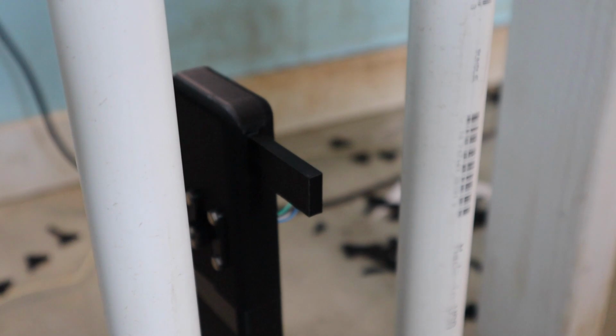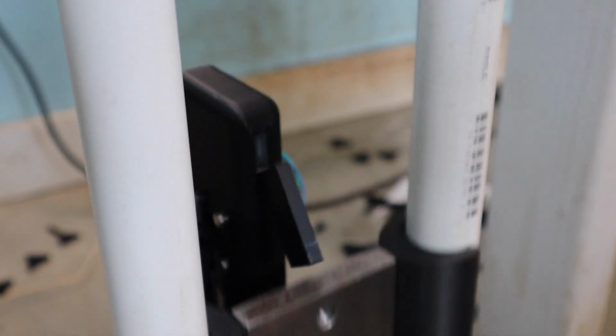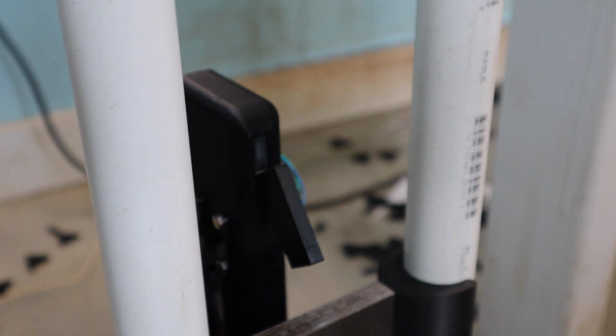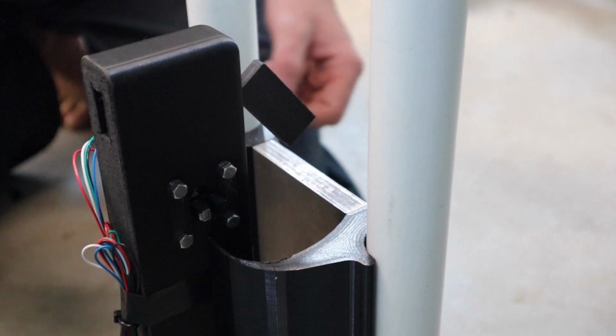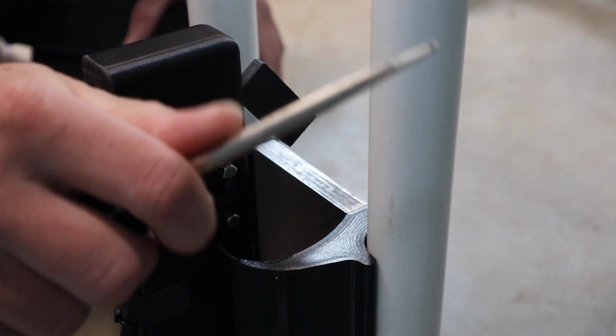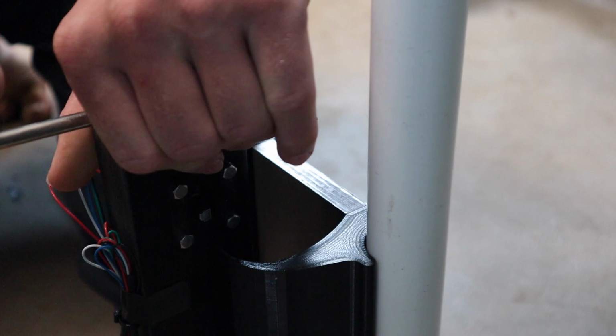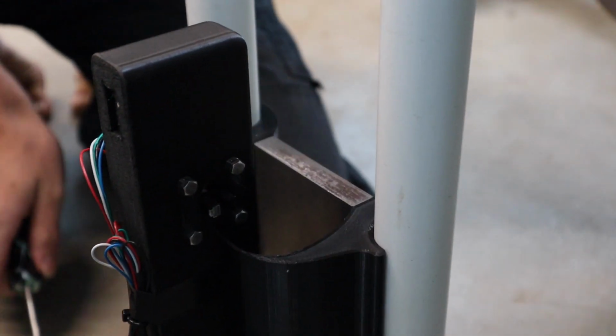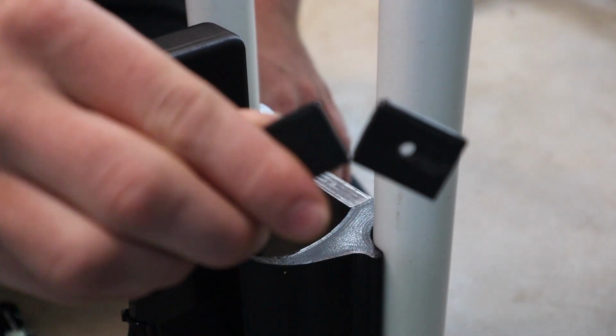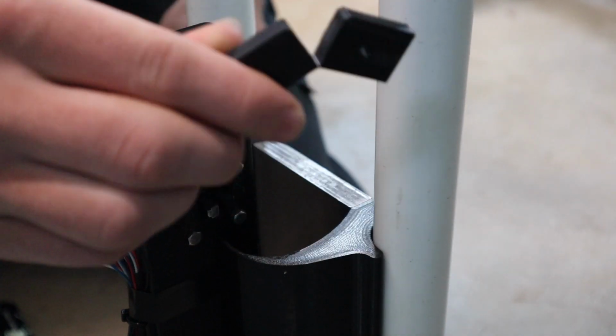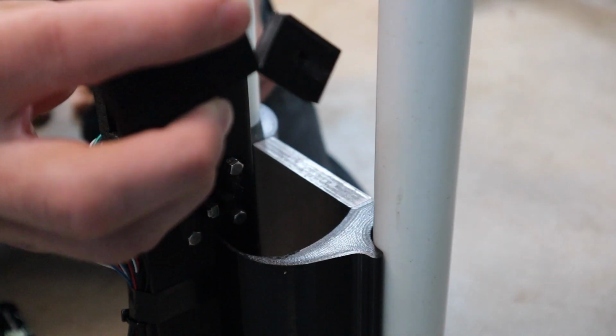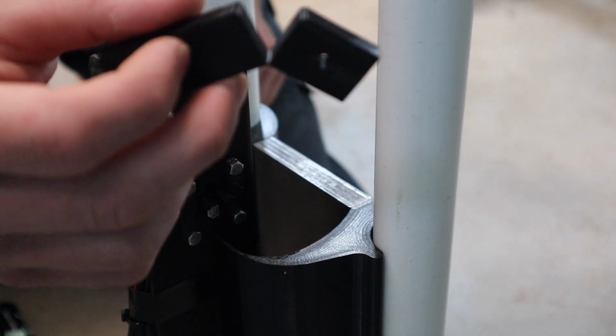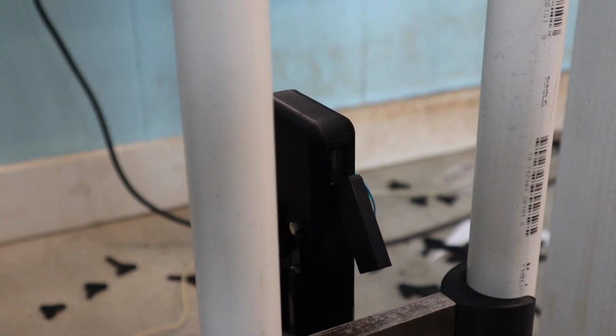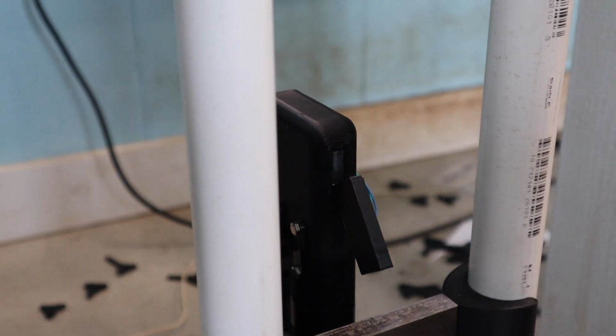Ready, set, go. 4.5 foot-pounds. We're going to take our official sample remover right here, and just press the sample out from this side, like so. So you can see our sample broke off at the notch like it was supposed to, and it absorbed 4.5 foot-pounds. Let's break the other two and see if we get consistent results. 4.23.